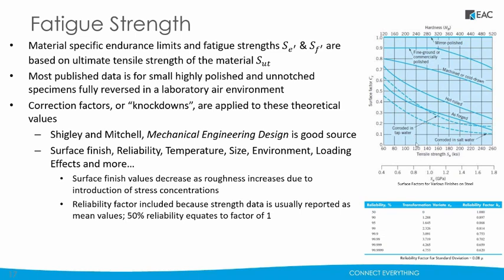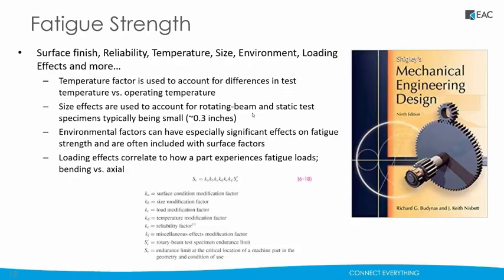So just as an example, if we take 120 KSI tensile strength, we come to a machined specimen, you can see we have a surface factor around 0.7. So you've already lost like 25% of your allowable stress, just taking into account the machining and that it's not a polished specimen. So it's a non-trivial thing to include. And reliability factor has the same thing. It drops things down by easily 20%. So by the time you add in your safety knockdowns, let's say your allowable stress on the specimen was 100 KSI, which is, I know, a big number, but by the time you do the knockdowns, it's going to drop down to about 40 KSI. You're going to lose more than half of the allowable stress that you get off an SN curve.